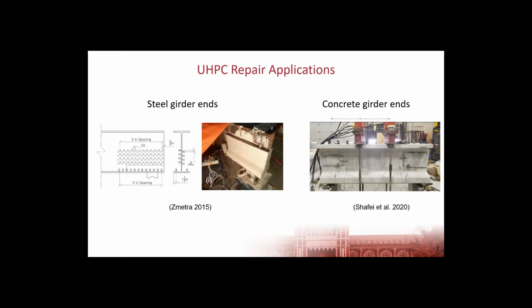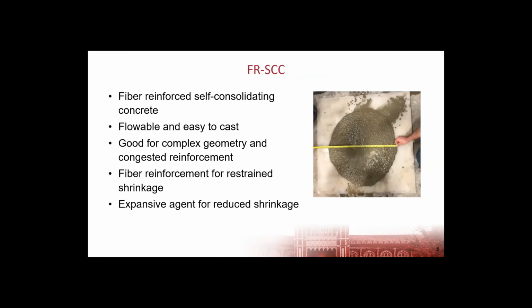So this webinar is primarily focused on UHPC, and that is the main point of a lot of the work that we've been doing. But in fairness to the rest of the project, we've also been considering some other innovative concrete materials, such as fiber reinforced self-consolidating concrete. So we have very flowable concrete that compacts under its own weight. It's also easy to cast, can be cast into complex geometry and congested reinforcement without the need for vibration, and then includes fiber reinforcement and an expansive agent to reduce and prevent any detrimental effects from differential shrinkage between the repair and the original material.